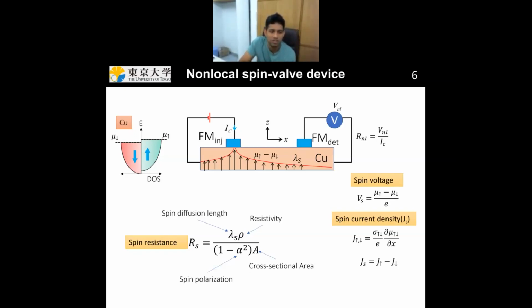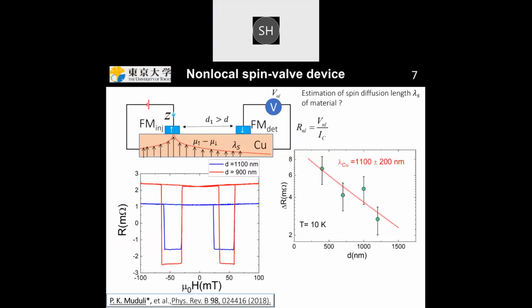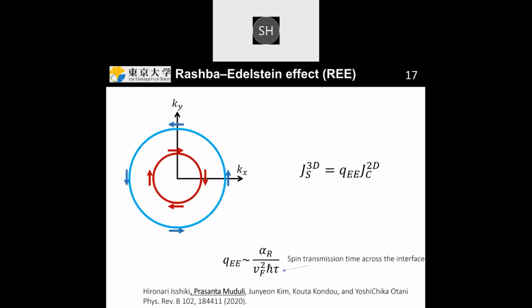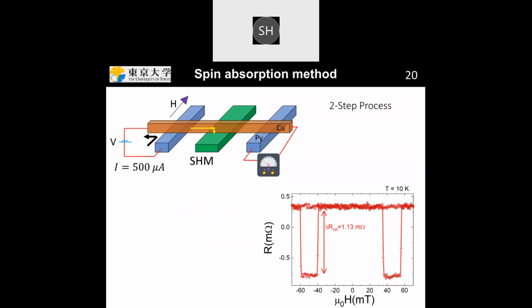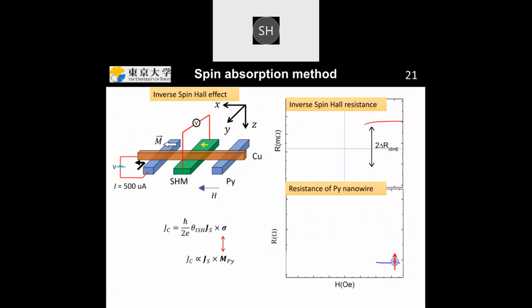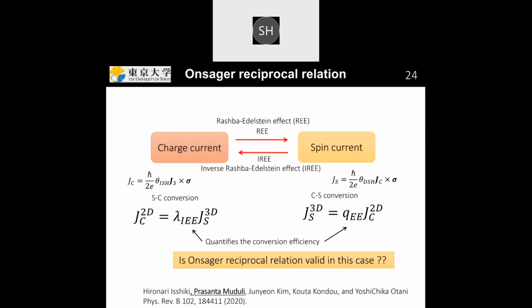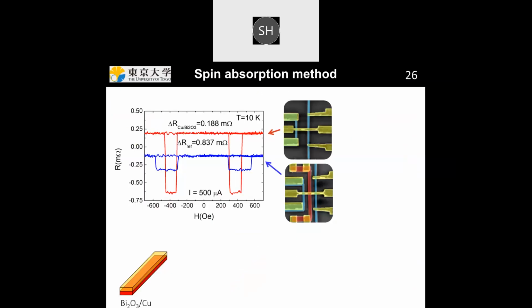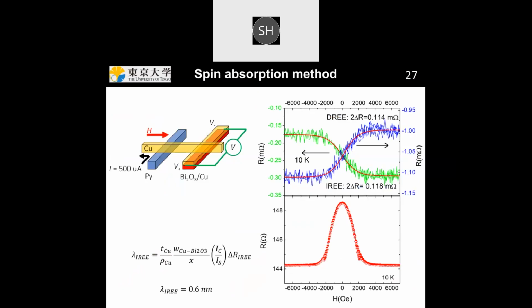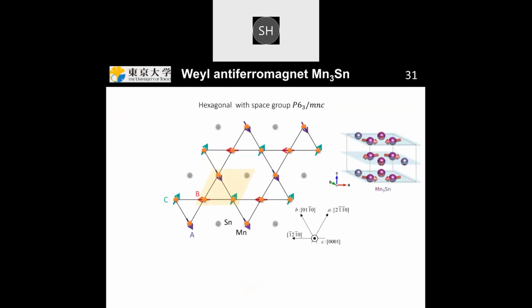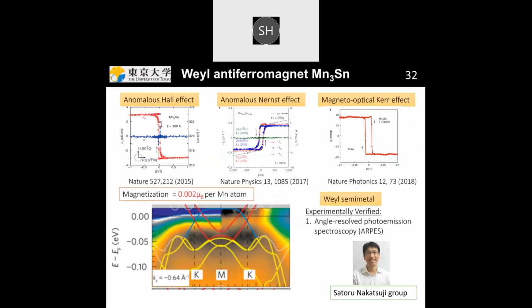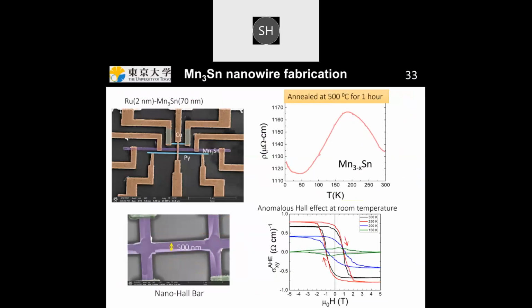I have just one basic question. Thank you, Dr. Muduli, for very excellent work and an excellent talk. One question regarding the non-collinear antiferromagnet. This non-collinear antiferromagnet has a directional dependence, an anisotropic spin Hall angle, especially for example in the Mn3Pt case. If the orientation of your crystal is different, if you inject your current in a different direction, you have different spin charge conversion, a different spin Hall angle.